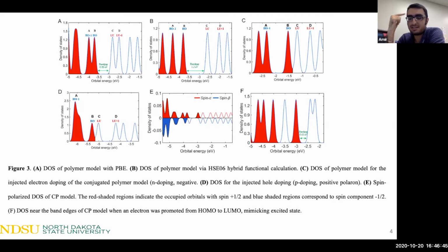So you should measure the distance between the tops of the peaks. If one peak corresponds to only one orbital, one should measure the energy offset between the tops of the peaks, not the overlap, because it depends on the width parameter, which is in some sense an arbitrary choice of the researcher. Oh, okay, my bad. I got it. Thank you for clarifying.